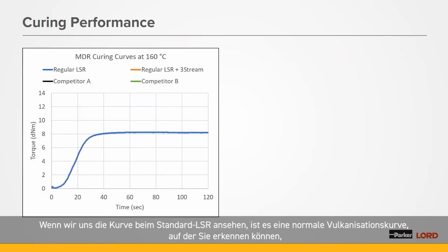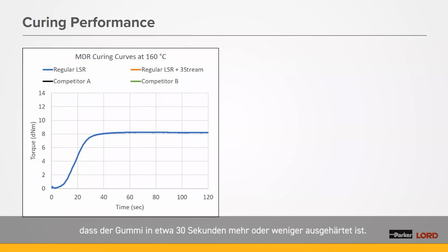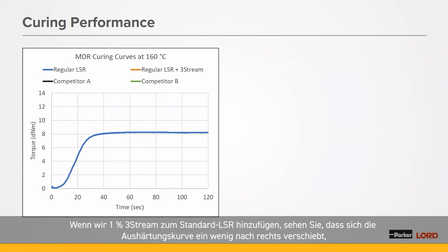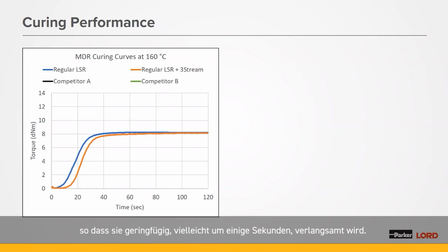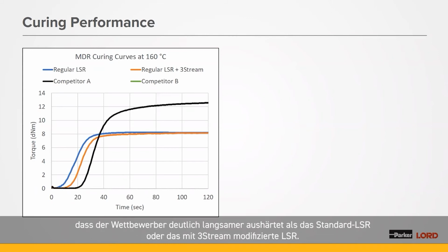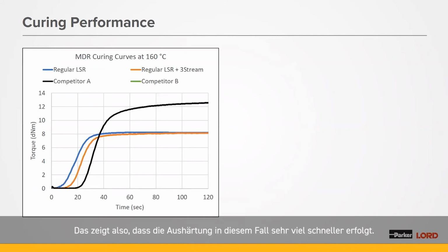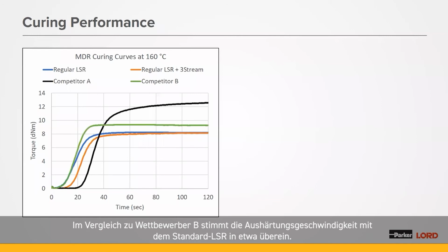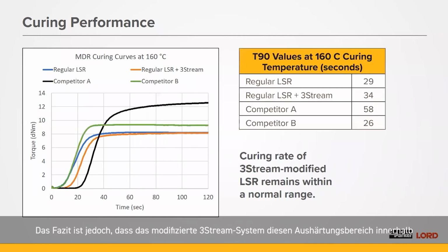When we look at the curve for regular LSR, that's a standard normal looking cure curve. You can see it's more or less cured in about 30 seconds. When we add 1% 3-stream to the regular LSR, you can see the cure curve shifts a little bit to the right, so it does slow it down modestly, maybe by a few seconds. However, when we compare it to competitor A, competitor A is significantly slower in curing than either the regular LSR or the one that's modified with 3-stream. So that shows that we cured a lot faster in that instance. Now compared to competitor B, it's got about the same cure speed as the regular LSR. But the bottom line is that the 3-stream modified system maintains the curing within a normal range for LSR.